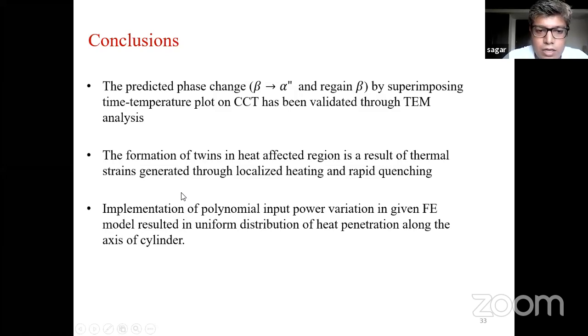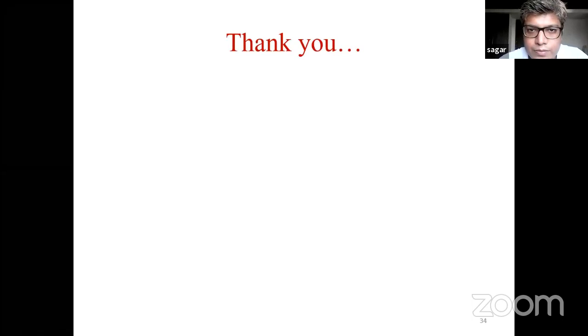twins. Then we have implemented this polynomial input power variation in the FE model to result in the uniform distribution of heat penetration along the axis of the cylinder. So when you get uniform laser penetration, you can decide your depth of cut for machining. With this model, you could get a constant depth of cut and go ahead with your machining and reduce the cutting tool cost. Okay, that's from my side.